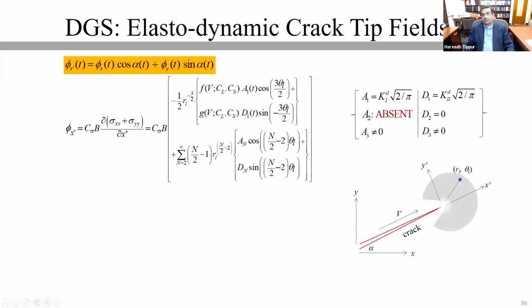In this case, as you saw, we were able to actually capture the crack tip fields. So we are able to measure the stress intensity factors at the tip of a growing crack. We did that using the 2 measurements, phi-x and phi-y. We converted them into angular deflections in local coordinates. X prime is the crack growth direction, and y prime is normal to the crack growth direction. X and y are your global coordinates. Alpha is the angle between the local and the global coordinates here.